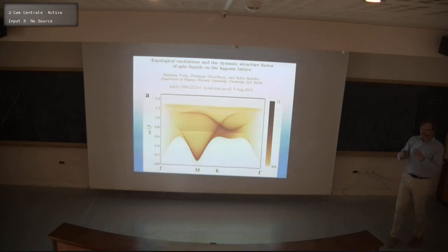And one of them is, if you remember from the beginning, I said that in a multi-particle excitation, I would have a lower threshold, a certain amount of energy required to create these 2 quasi-particles. It costs energy to create it, and depending on my center of mass momentum, this threshold will actually vary through momentum space. But actually, at every momentum transfer where we see excitations, it seems to just come all the way down to almost 0 energy.